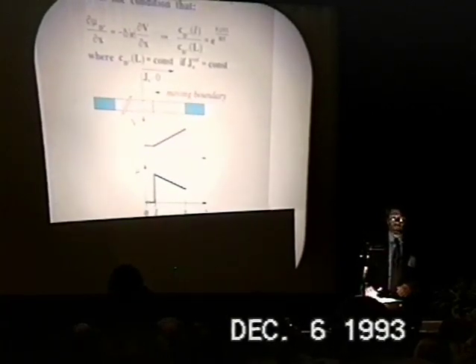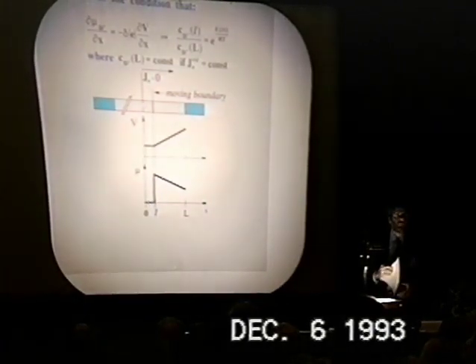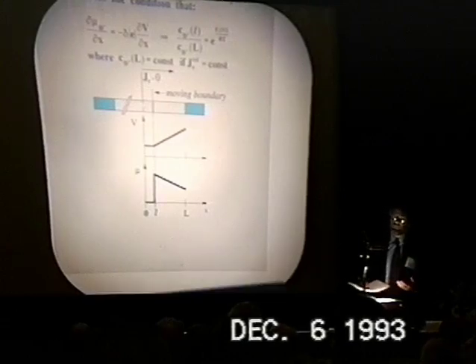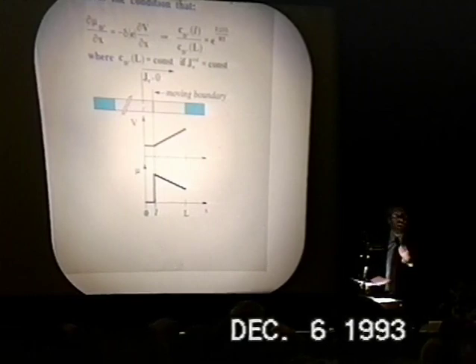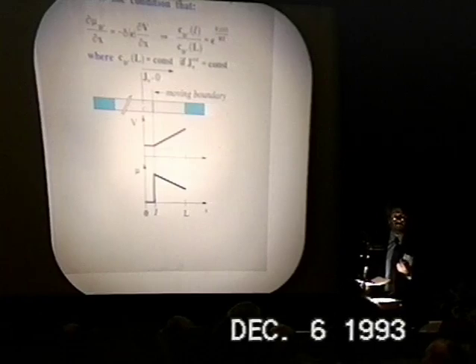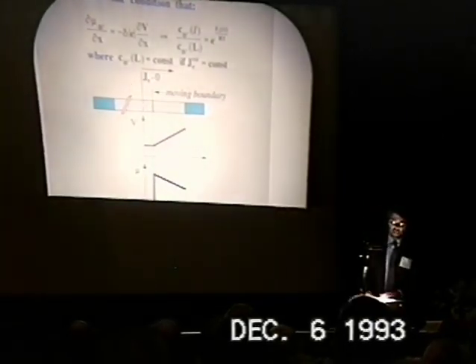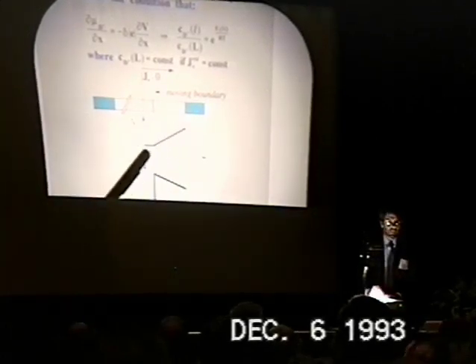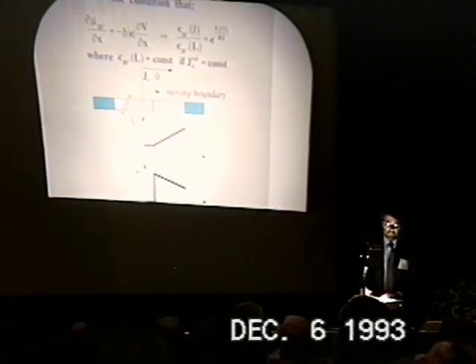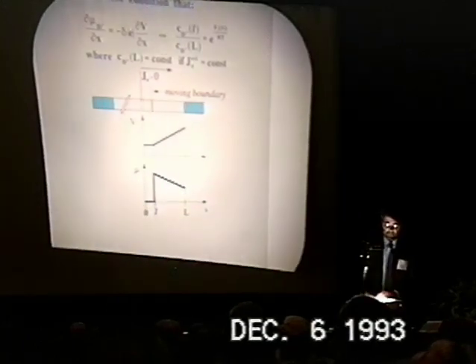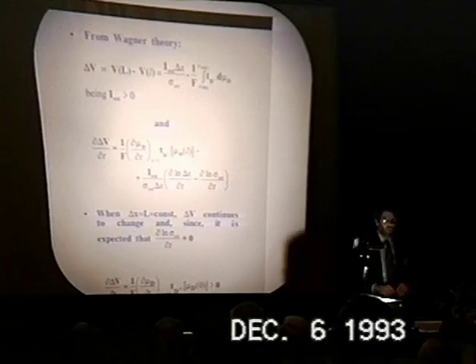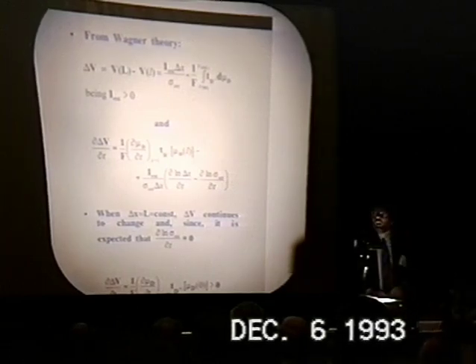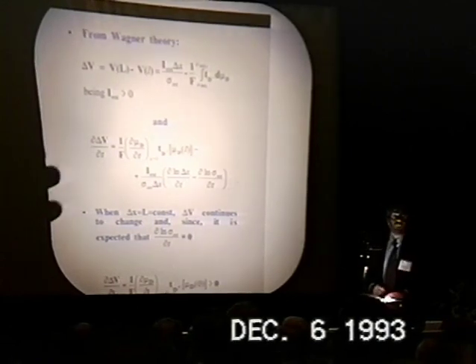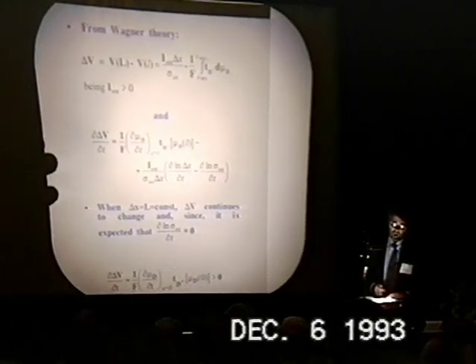Deuterium goes into palladium, but not with a simple diffusion process. It's a process assisted by the electric field, because when a layer of deuterium is formed, in this layer an electric field is generated by a flux of electrons which crosses the layer. So, in this way, inside this layer we have this trend of voltage and this trend of the chemical potential of deuterium. We can treat this data on the basis of Wagner theory. Wagner theory was used to calculate the kinetics of oxidation of metals and ionic products.